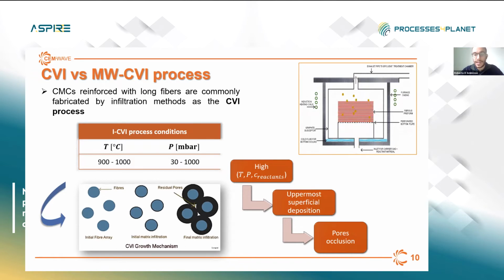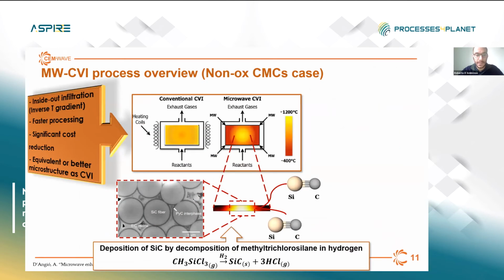However, in conventional isothermal isobaric CVI, high vacuum levels are needed to favor the penetration of the reactive gases inside the preform, leading to a strong depression of reaction kinetics with resulting processing times also of several weeks to achieve the final density. So one of the solutions to overcome the low deposition rates observed in conventional CVI is through the application of thermal gradients within the preform.